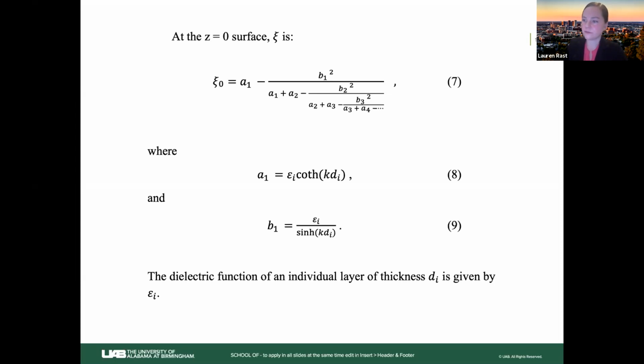For silver and for the other metallic materials, we used empirical values from the literature, in the paper that we wrote on this with two of my collaborators. Johnson and Christy have a paper that is very widely used for empirical values of dielectric functions for metals and thin metals. But for the 2D materials, what was used is density functional theory.